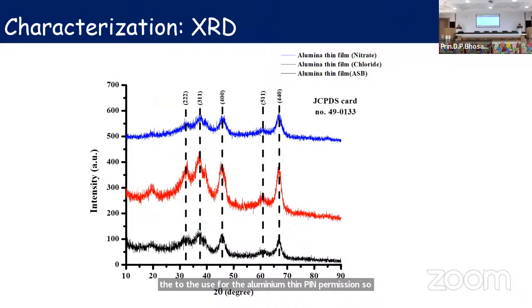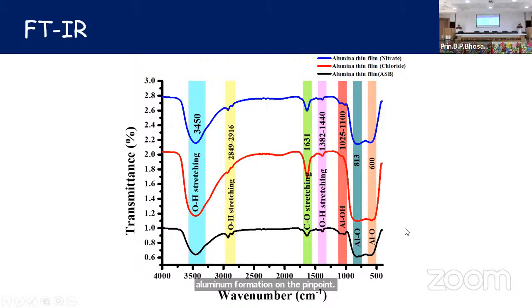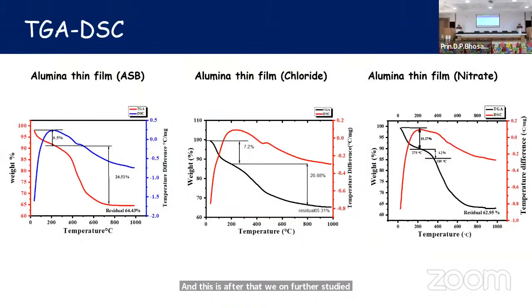So here are some characterization results of all of these thin films. They are all confirmed using JCPDS card number 49-0133 to confirm the alumina formation on the thin film. Then FTIR also confirms the Al-O bridge. There is the presence of Al2O3 formation in this thin film, confirmed by FTIR analysis. After that, we further studied their thermal gravimetric analysis using TGA, from which we can say that up to 800 degrees Celsius, all three alumina structures are stable. We can conclude from these results that the alumina structures are stable up to 800 degrees Celsius.